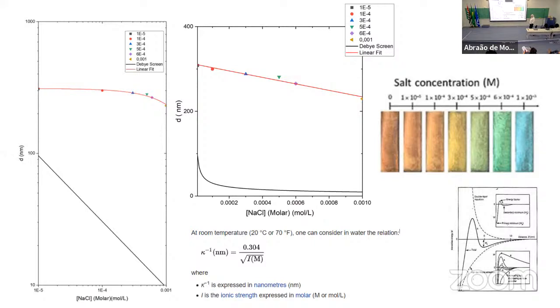Because I mentioned DLVO, which is a combination of van der Waals and electrostatic repulsion. And the electrostatic repulsion is tuned by adding salt to the water. These dark lines here is what you expect from the DLVO, and our distances are far away. But still, we can control the color by adding salt to the water. We tried that because we know about DLVO, of course, but it does not follow the DLVO model for this.